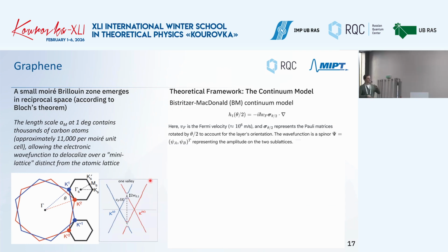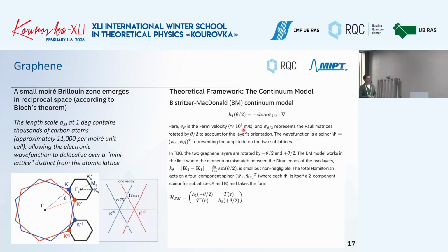First of all, in order to make this continuum model, a theoretical framework description of twisted graphene, you take the Hamiltonian in a single layer, with a very high Fermi velocity, this linear dispersion, and so on. Then if they are rotated by theta degrees, one is described by plus minus theta divided by two. This model works in the limit where the momentum mismatch between the Dirac cones of the two layers, depicted like this, is very small, but not negligible. So the total Hamiltonian looks like this.